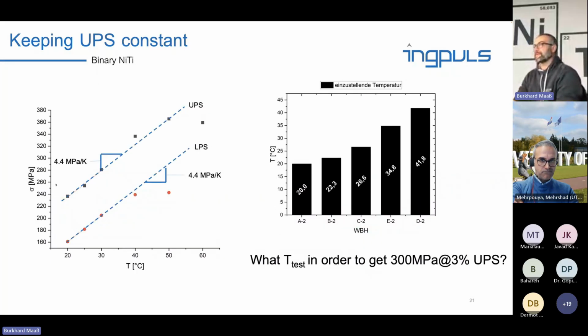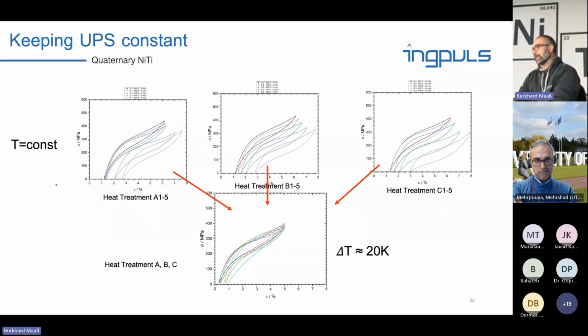So we said we wanted to look into what test temperature we have to apply to have 300 megapascal at a 3% elongation, and to see if we can get this really constant. And so Alex spent a lot of time in the lab between heat treatment furnace and tensile tester and climate chamber, and this is what we got out. So we had a large program of heat treatments, and this is always the same diameter and the same alloy composition and different heat treatment parameters. And then we go to different test temperatures, and we achieve that they have all more or less the same mechanical response. And this is what we want for a cascaded system. So now you can have the same mechanical frame for your machine operating at different temperatures.